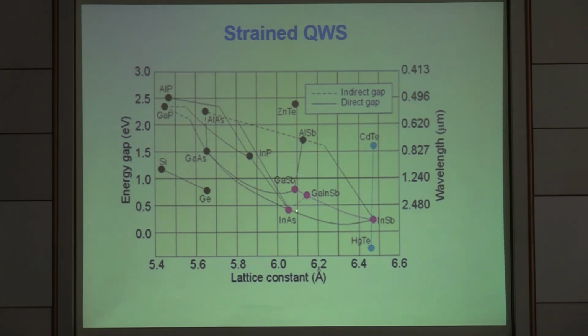If we look at this material, indium arsenide and gallium antimonide, they are basically lattice matched. This is about 6.05. They have very small lattice mismatch. Now, if we consider putting in some indium, we find that this lattice is going to mismatch. So if you grow this gallium indium antimonide on top of indium arsenide, you have lattice mismatch. The epitaxial growth is going to compress this whole layer, or a valence band layer. And as a result, the band structure of the whole is going to change dramatically.